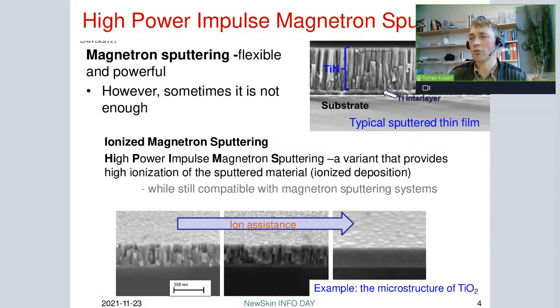However, as an example, I'm showing a typical titanium nitride thin film. As you can see, typical thin films or coatings are columnar, which is not always bad, but sometimes the existing coating is simply not good enough. What we do here in Uppsala and what we offer in the NewSkin project is modified magnetron sputtering, where a large part of the material being deposited is no longer neutral atoms, but rather ions. Because we are using ions, we can provide more energy to the growing film, and we can make it denser and in general better.